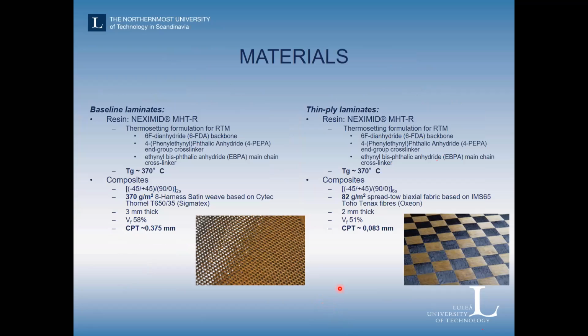So what we have done is show some results from a study that we've conducted, where we used this material on the right, thin ply materials, with really low surface density fabrics that create really thin plies. And the idea here is that we know from previous work that thin plies have a tendency to prevent this transverse cracking that could be caused, for instance, by thermal stresses. And we wanted to see if by introducing thin plies to prevent these cracks, we could decrease the aging of the materials.